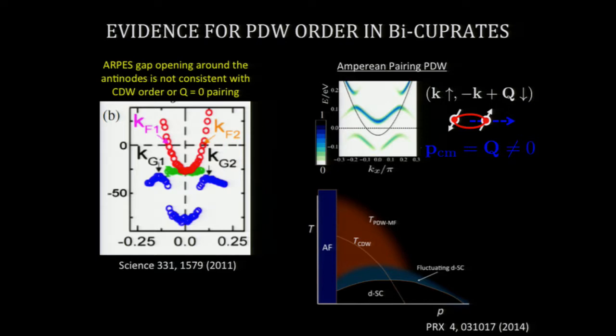And this led Patrick Lee to propose that perhaps one can explain this phenomenon by proposing that it is a pair density wave. So he comes up with a mechanism by which, without a magnetic field, you can get k up and minus k plus q down to pair to give rise to a pair density wave in the system. And he even comes up with a phase diagram for it.